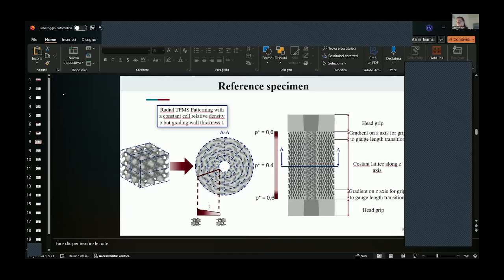And then in order to avoid crack formation in correspondence of the interface of the head grips and of the constant lattice part, we have a gradient zone in which, again, varying the wall thickness, we have a gradient of relative density from 0.4 to 0.6. And this is a layered structure. So looking at the specimen in the right part of the slides, we have 12 layers of the A section that we can see.